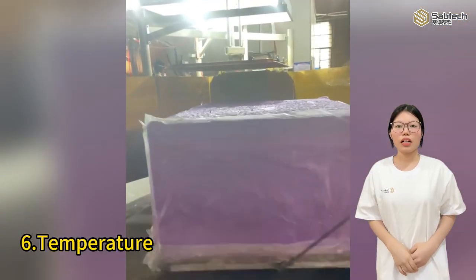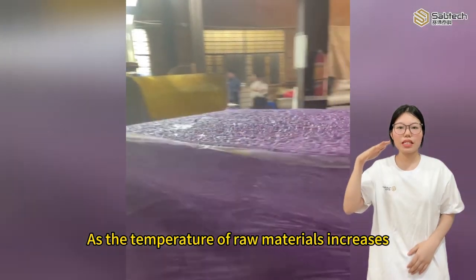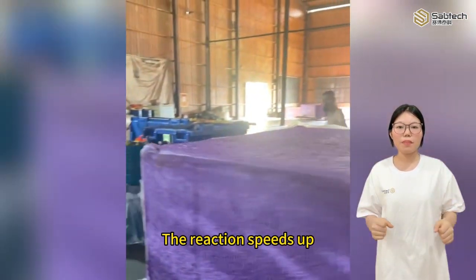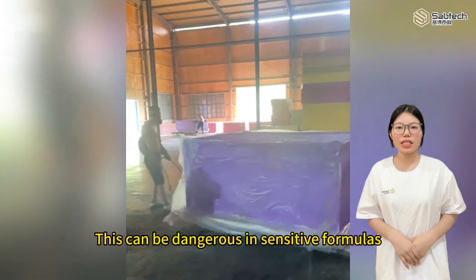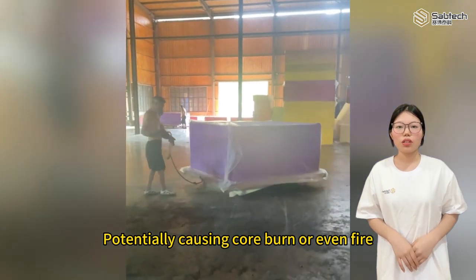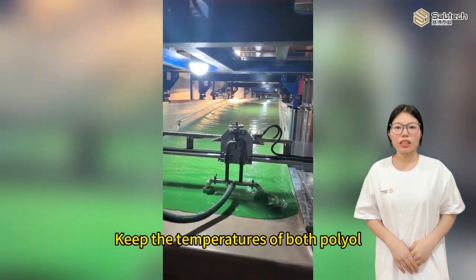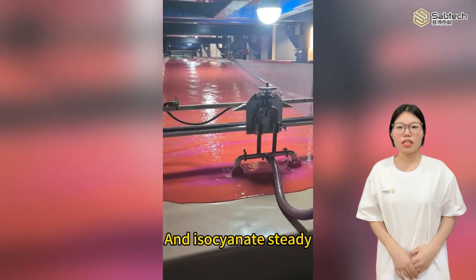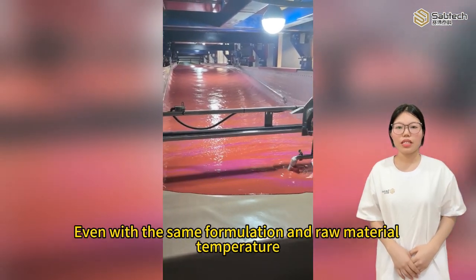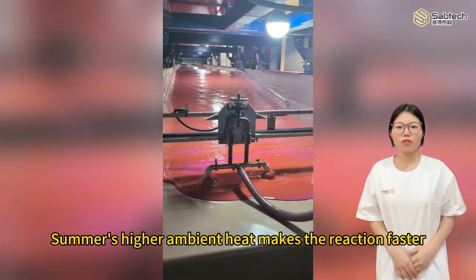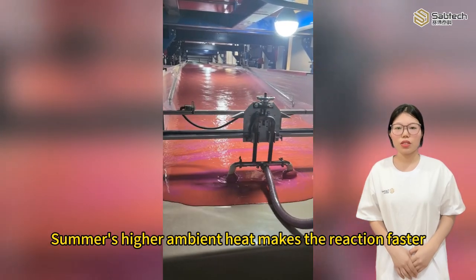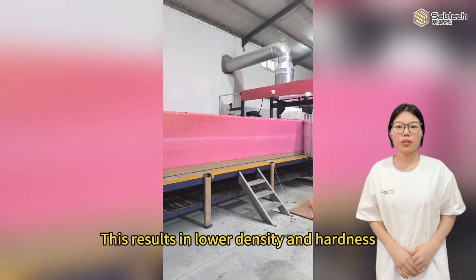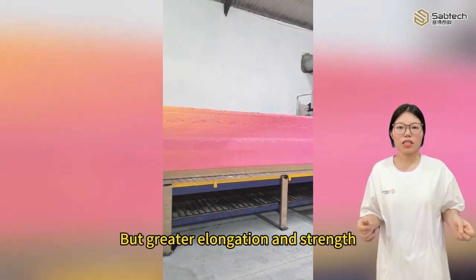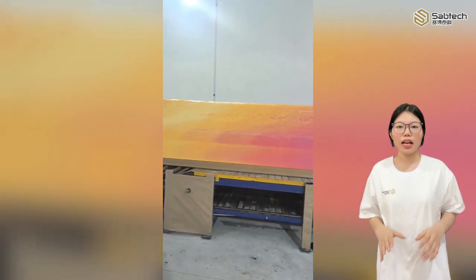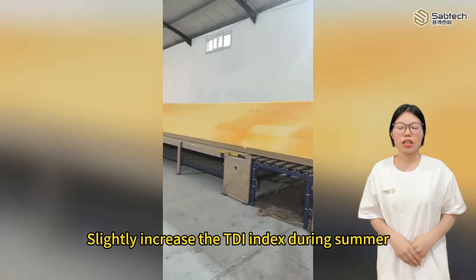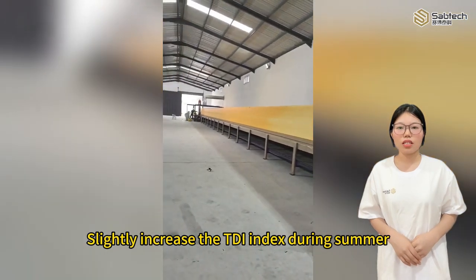Sixth, temperature. As the temperature of raw materials increases, the reaction speeds up. This can be dangerous in sensitive formulas, potentially causing core burn or even fire. Keep the temperatures of both polyol and isocyanate steady. Even with the same formulation and raw material temperature, summer's higher ambient heat makes the reaction faster. This results in lower density and hardness, but greater elongation and strength. To maintain proper hardness, slightly increase the TDI index during summer.